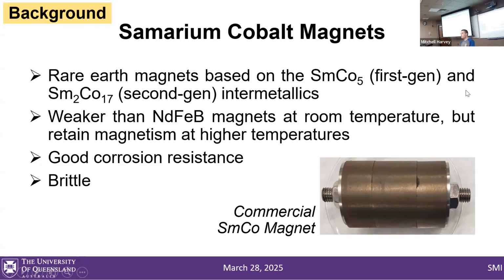Oh, another interesting property I forgot to mention is that the 217 magnets are cool. So if you add gadolinium to them, which is another critical material, that reversible temperature coefficient becomes almost 0. So you can have magnets that have a constant field strength over a fairly wide temperature range.